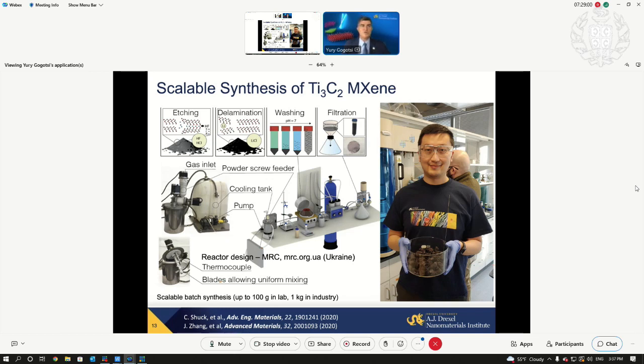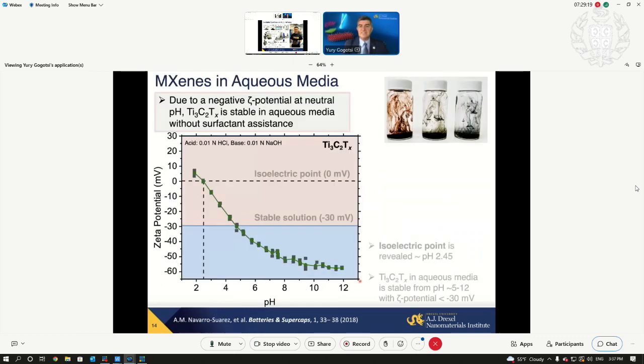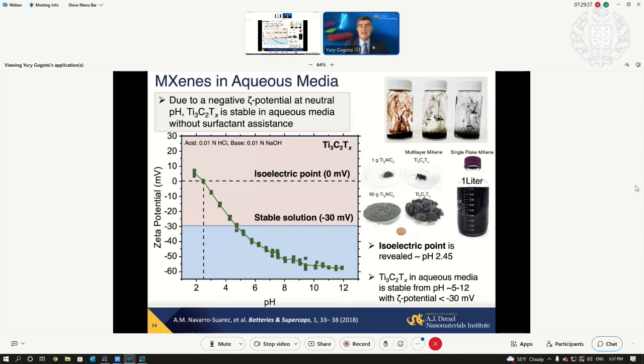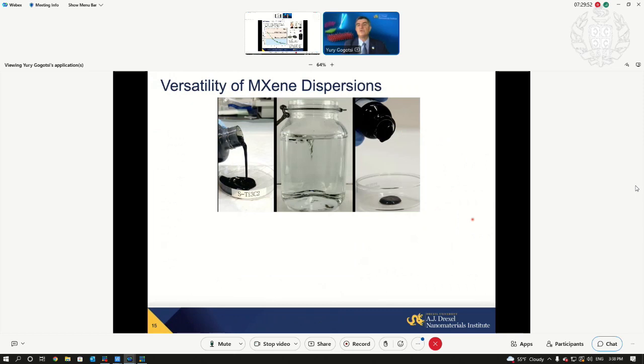You can see one of my postdocs, John Zhang, holding 1 kilogram of MXenes made in our laboratory using reactors designed by MRC Ukraine for us. So, scalable synthesis is possible. So we have a variety of materials. We can produce them at scale, even in the lab. And moreover, since they typically have oxygen, OH termination on the surface, they have a high negative charge on the surface. So what does it mean practically? They can be dispersed in water without any surfactant, binders, without any additional toxic chemicals that need to be burned after that here. So we start with ceramic powder, we etch it, make MXenes. Sorry, I don't have time to talk about the details of how we do it. And we end up with this colloidal solution.